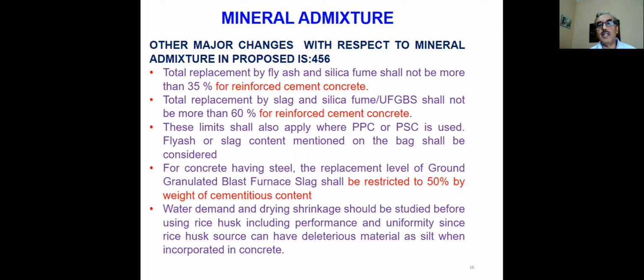Similarly, total replacement by slag and silica fume shall not be more than 60%. This is for mixing at site, not in the cement as such. These limits shall also apply when PPC or PSC is used, because even if you are using PSC, you cannot put additional silica fume if the slag already present is 60% or more, since that also increases further carbonation. The limit of PSC of 70% is actually too high - that also needs to be revised in due course.